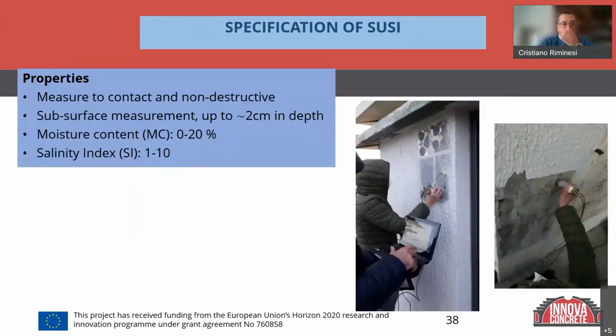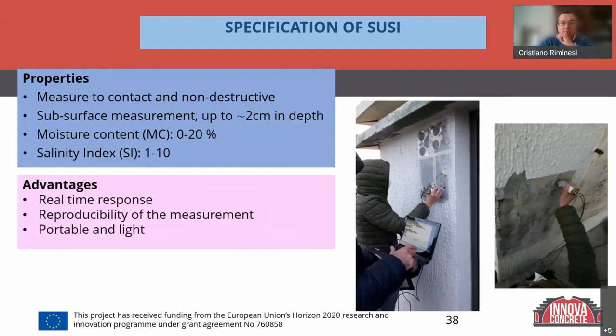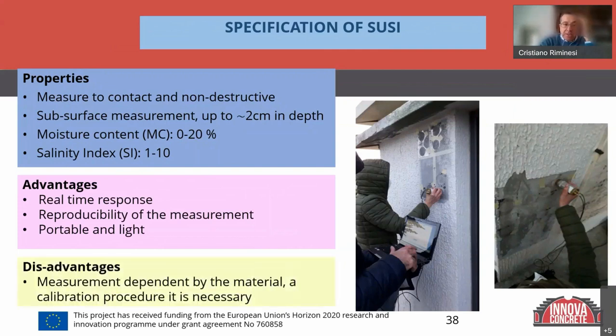So by this measurement, we can also measure the salinity, the presence of salt in the material, through the measurement of conductivity inside the material with this particular microwave approach. The response is in real time. The device is completely portable and the measurement is very reproducible. The only disadvantage is that we need a calibration procedure. So before starting our investigation, we must take some samples and perform the measurement in the dry state and in waterlogged condition.